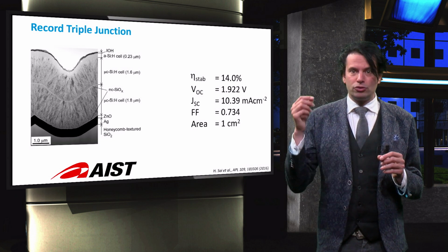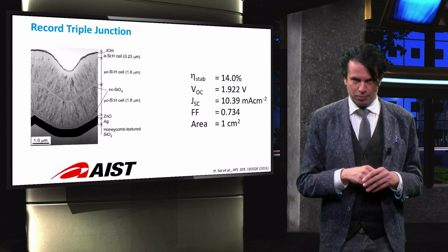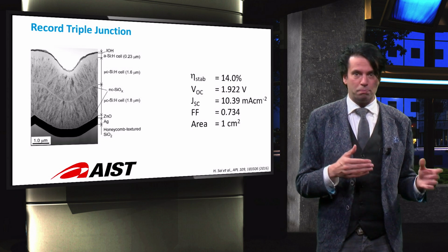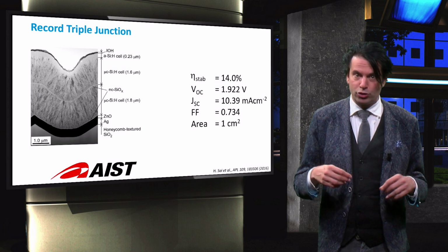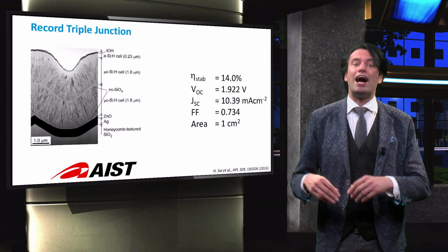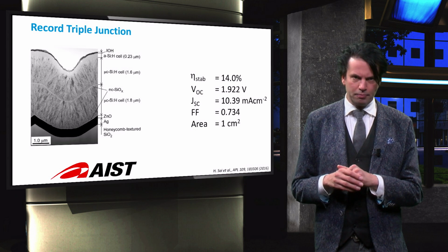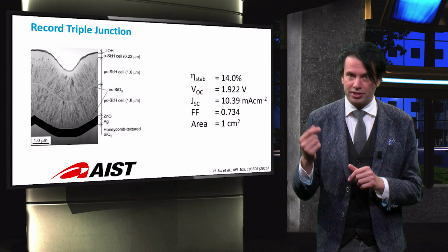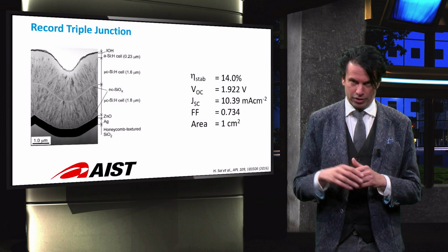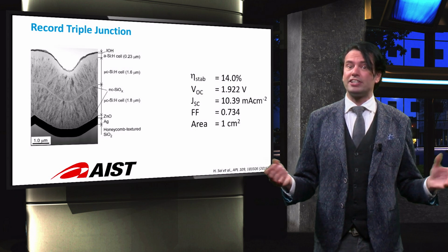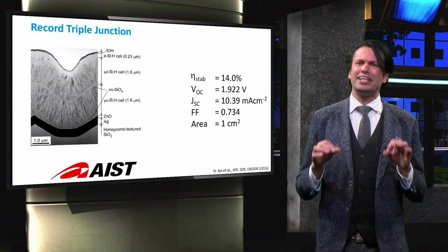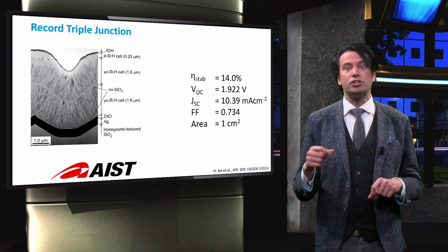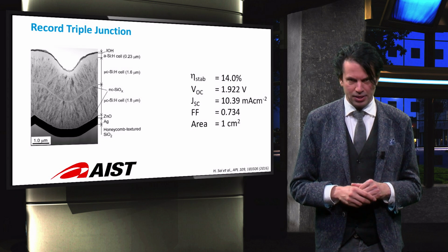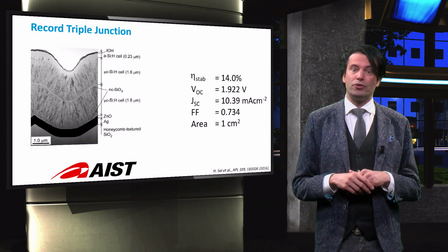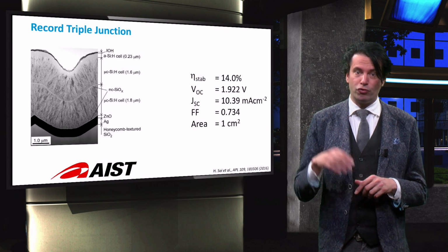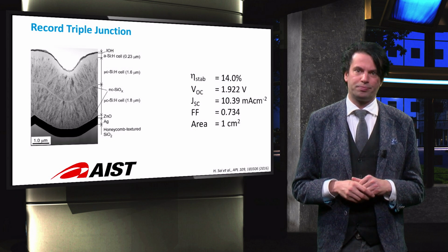Researchers have combined two innovations we discussed earlier. Again, the innovative honeycomb structured back reflector was used as substrate to facilitate good light trapping and the growth of high-quality nanocrystalline silicon. This is similar to the single junction nanocrystalline silicon NIP solar cell with the record efficiency. The additional innovation is the integration of dense, high-quality intrinsic amorphous silicon in the top cell using the triode PECVD technology. This innovation resulted in the record stable conversion efficiency for amorphous single-junction solar cells.